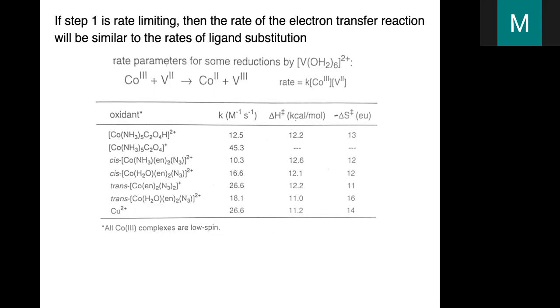Right, it's always going to be a dissociative reaction, and it's going to be dissociation of water from vanadium-2 plus, forming the bridged intermediate via either oxalate or azide. And then the subsequent steps must not be rate determining. And so here we can see part of the reason that this makes sense is also that this is really pretty much the same rate at which vanadium-2 does ligand substitution reactions.